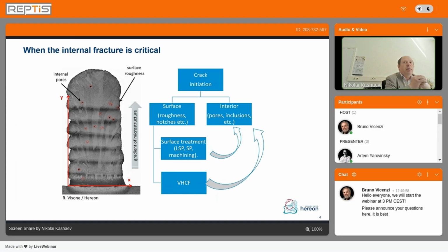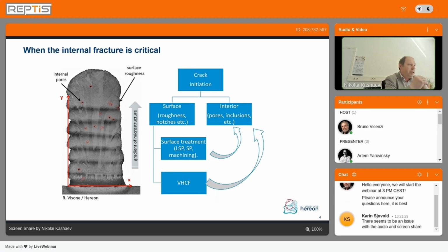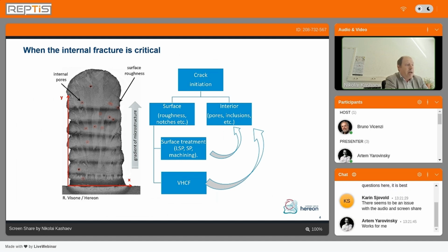However, if we consider load-bearing components, nobody will apply the components with the surfaces in as-built condition. We have to apply some technologies to reduce the stress concentrations from the surface. We can, for example, perform surface treatment or machining. And then internal defects will play a significant role. The internal defects will be also critical, for example, if we go to very high cycle fatigue behavior of the component.